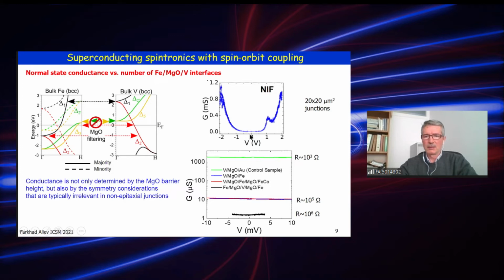If you see on the IV characteristics, the conductance is quite small, and this is evidence for some band structure features. All current, as I mentioned, is due to spin-orbit coupling.